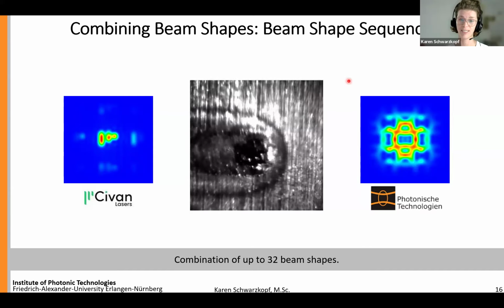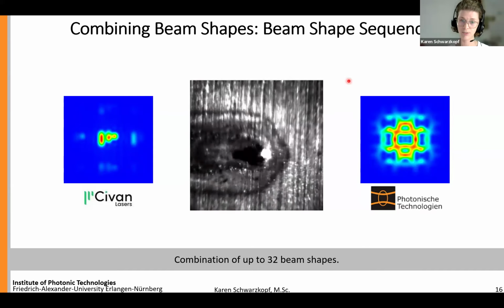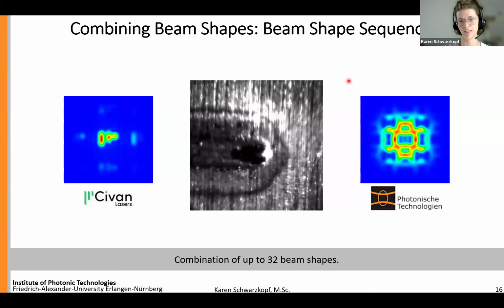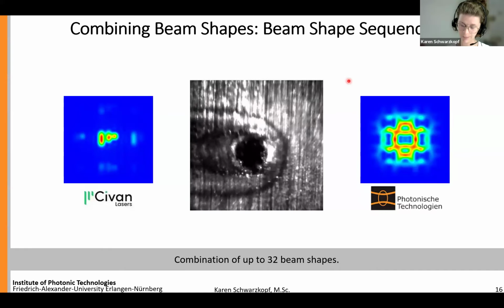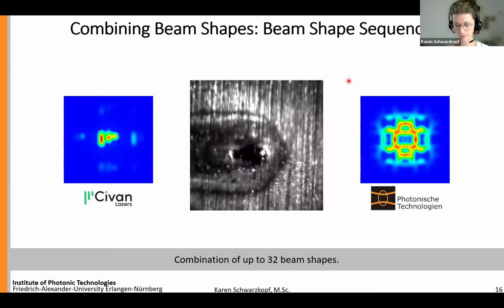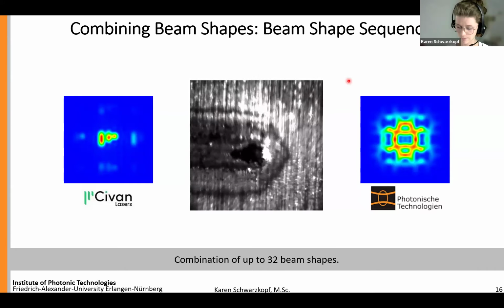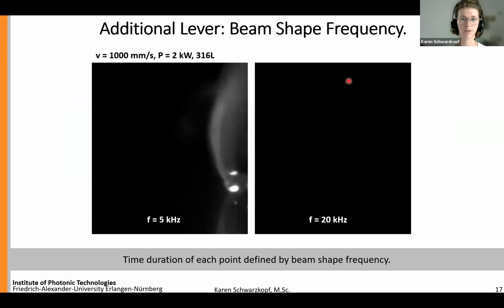Since we are not putting a mask of intensity distribution on our beam shapes, but we are rather scanning our beam shape, there's also a third characteristic of the laser, and that's the so-called beam shape frequency. This basically defines how long each point is resting at a position in time. And just as an additional lever, I wanted to show you a short video that demonstrates that this beam shape frequency also is really influencing our process.